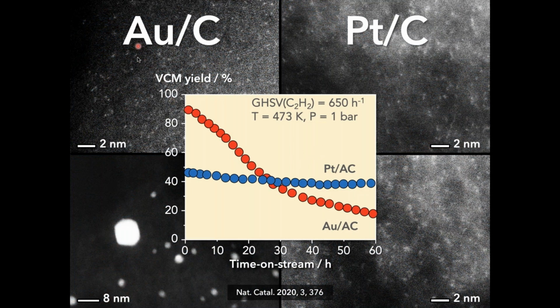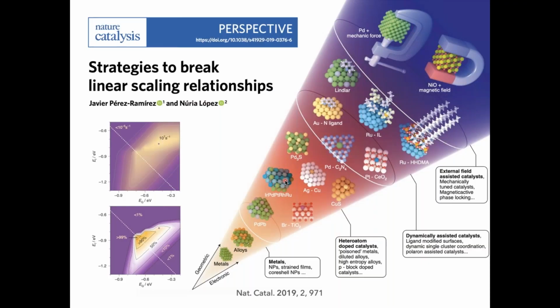Gold is extremely active in the beginning as single atoms, as you can see here in red, but during time on stream, it heavily deactivates because it is mobile, and it sinters into these huge gold nanoparticles that are inactive. Now, platinum single atoms are less active because they are more attached to the host. However, because of their unique stability, already after 30 hours on stream, they are superior to the gold system. So this is a trade-off between initial activity and the real key aspect, which is stability of a catalytic material.